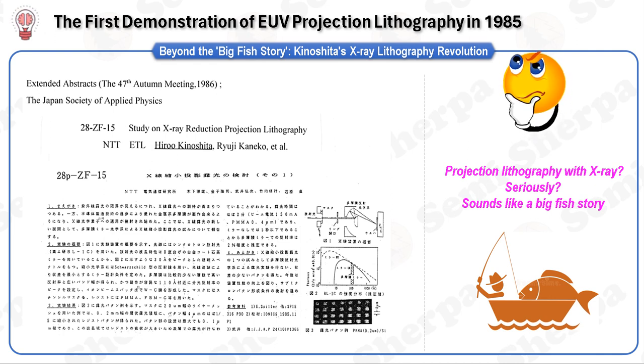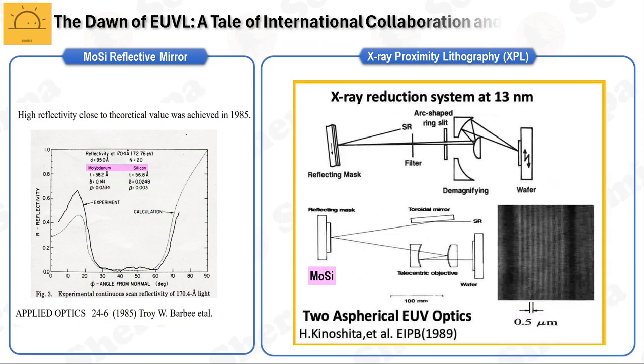To provide some context, this achievement is recognized as the first demonstration of extreme ultraviolet projection lithography, EUVL. It's worth noting that during that period, the term EUV, specifically wavelengths between 4 to 40 nanometers, was referred to as soft X-ray. In 1985, a groundbreaking discovery was made by Troy Barbee Jr. and his team. They developed a molybdenum silicon, MoSi, multilayer that achieved a reflectivity of over 70% at around 17 nanometers. This was a monumental achievement, marking the first instance where reflectivity approached the theoretical value.